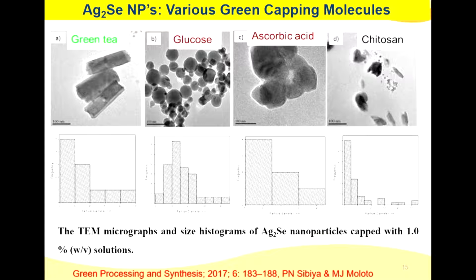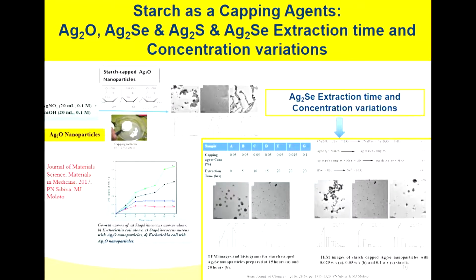What are the kind of variables that control or perhaps can play a role in growth of these nanoparticles? And you realize that glucose is still much better than ascorbic acid and chitosan. And the green tea also shows some, these are very big particles which are not spherical, which are non-spherical. But you can see that now, at least with green tea, there's some variable that comes to play a role there. And you try to say, okay, maybe we can just explore this starch a lot more,